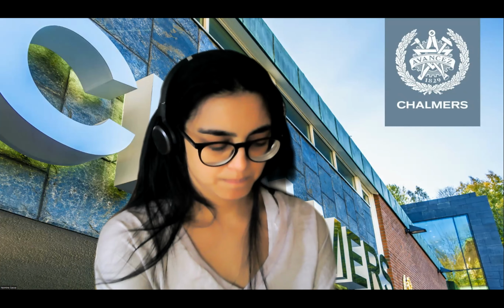Well, it's obvious that we can resolve part of the contribution from the A because of this. We could see that we have this anisotropy in the London penetration depth, and also we could see a hexagonal structure at low fields. It has been observed, this hexagonal structure at low fields and also in the intermediate field structure. So as far as I know, I can just say they are both important. They can be tuned with the calcium doping, and they can be controlled depending on the field that we are applying.